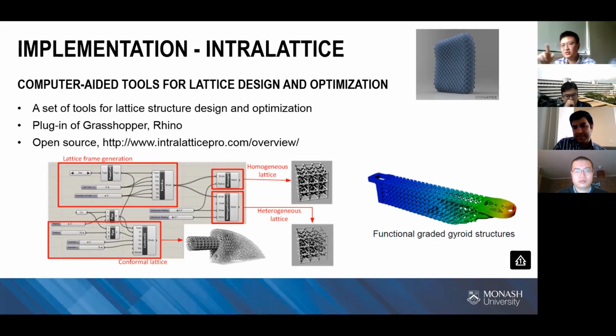In the past, the cooling channel would have a cylindrical cross-section shape. And we found if we use the lattice structures, it can have better heat convection performance. So we can cool down the mold really quickly, and that can shorten the production time. In the past, one part would take 6 minutes for a whole injection molding cycle, but with the lattice structures, it can reach 4 or 3 minutes.